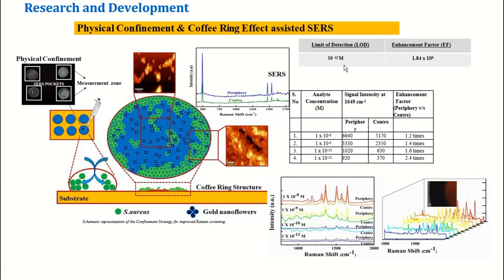Another problem with Raman spectroscopy is that once you take it on a chip or a silicon wafer or a glass substrate, the glass substrate gives very high background, so we prefer silicon wafers. But on the silicon wafers, you have to find where the Raman substrate is and where your Raman analytes are. So what we have done is a physical confinement in a microstructure. We have cast our nanostructures inside this micro confinement, so that once there is a coffee stain, you can see that it goes to the periphery. All the small analytes or small molecules always try to travel in the radial direction, outward.